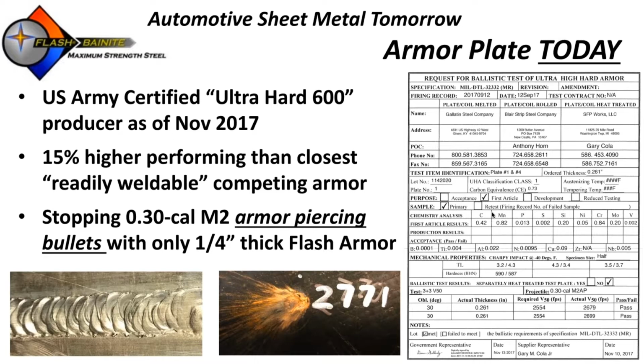And as you can see, the copper shattered to the left, there is no hole in our steel. And of course there was no backer plate or anything else. This was just a 1/4 inch plate. And we've done this multiple times. As far as I know, there is no US production source for an ultra hard 600 class 2 that can stop armor piercing at a 1/4 inch thick. And in the world, there is no readily weldable ultra hard 600 either. So there's a lot of applications here for bulldozers, dump trucks, and I guess armor plate as well.